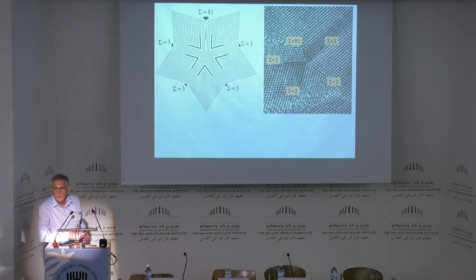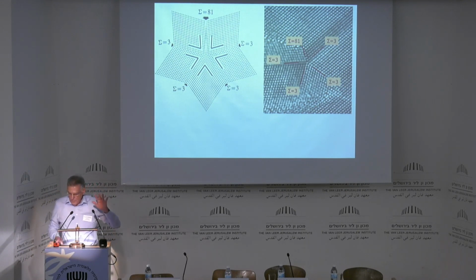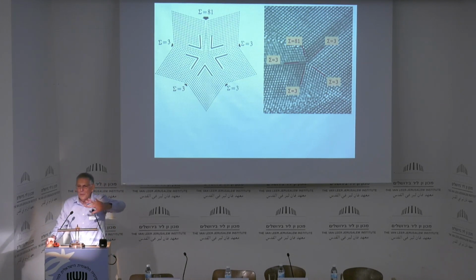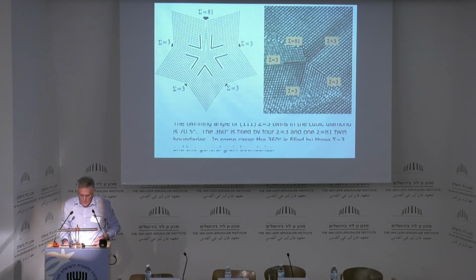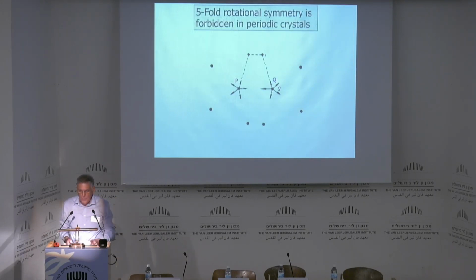Now, if you take a diffraction pattern, which you can do in the electron microscope, from all of them together, then you'll have 5 superimposed diffraction patterns. 1, 2, 3, 4, 5. And clearly, if you do that, you will have a 5-fold rotation symmetry diffraction pattern, but it is not taken from one crystal. It is 5 different ones superimposed. And this is what I thought. I'll show you another example based on my experience, but before that I'll show you why 5-fold rotation symmetry is forbidden.